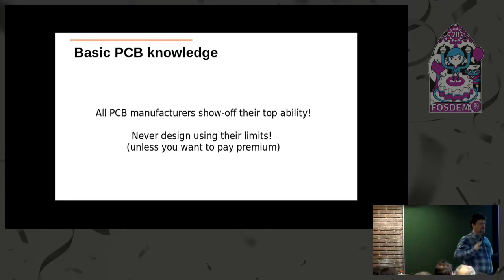Very important. All the manufacturers show off their best capability, but you never have to design with these capabilities unless you want to pay a premium, 2 times their prices, because for 8 mils, for instance, they have 0 problems. If you go to 6 mils, they might have 20% problems. Depends on the different manufacturers. How do I test them? I order 100 boards, and sometimes I get 116, 120. So they always run 20% above the quantity you order. And then if something failed the e-test, they ship it to you anyway because you paid for it. And if you want to go to 3 mils, for instance, they might have down to 50% scrap. But who pays for this scrap? You, of course. So if they say we can make 3 mils, never use 3 mils unless you have to.